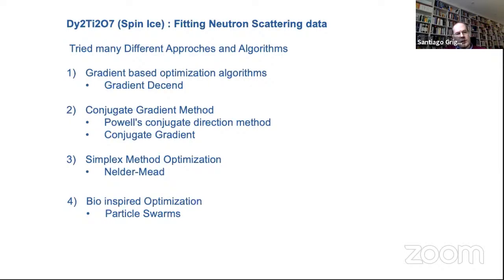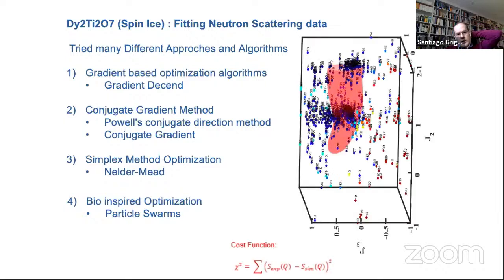So you can narrow it down a little bit in the sense that the dipolar term is determined by the distance between dysprosium atoms and the magnetic moment. And maybe you can use some other experiments to fix more or less J1, but at least it's a 3-parameter fit you need to do. So the one thing we did, which started working, is what I'm calling this bio-inspired optimization.